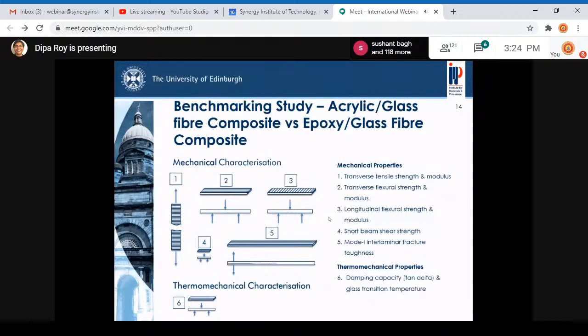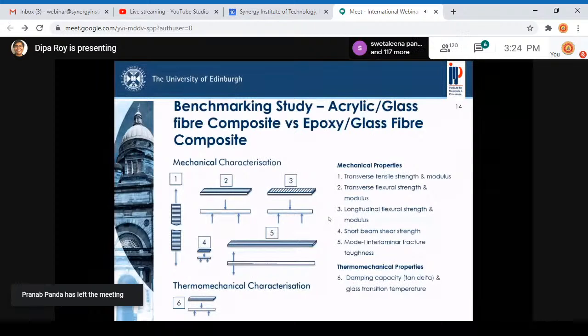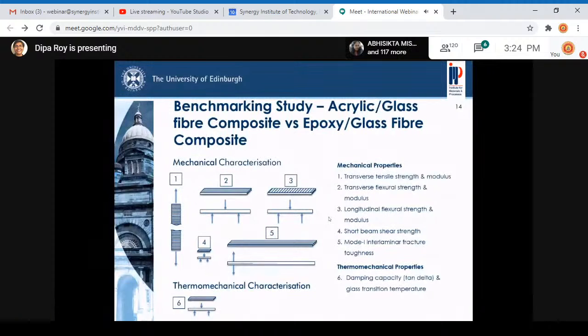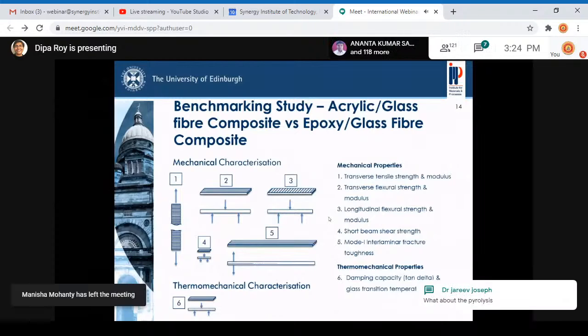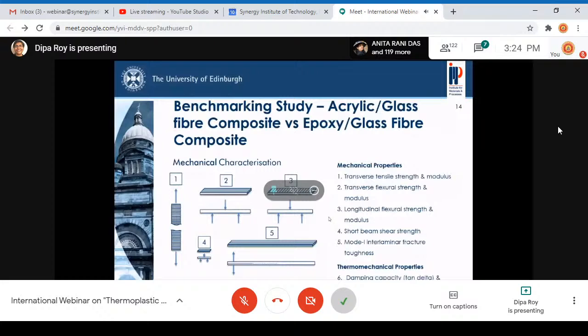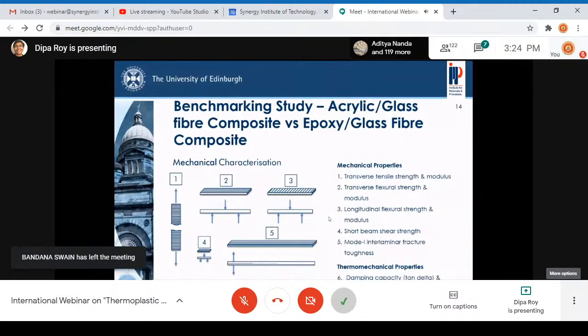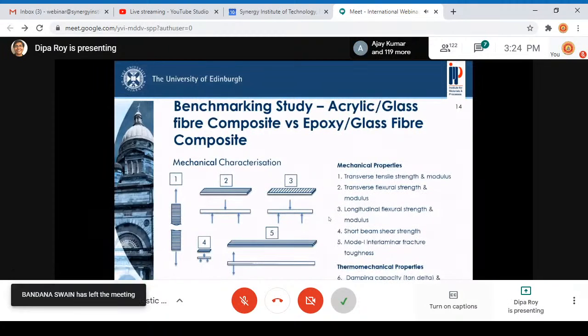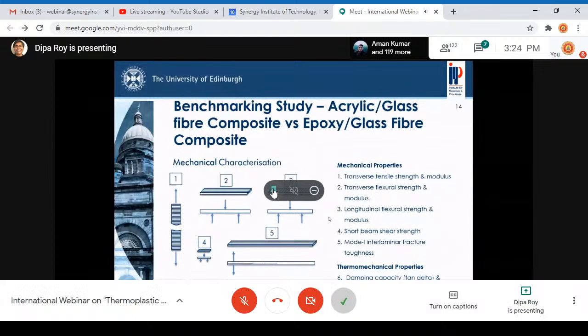So it has those silane coupling agents which have R groups, or organic groups, which are chemically compatible with different matrices. Now, since our acrylic resin is a liquid monomeric resin, it polymerizes in situ during the composite manufacturing. So there is a high opportunity of forming some covalent bonds between the resin and the sizing agent in situ. That's a big advantage of acrylic resin, because we get a chance of forming covalent linkage between the sizing agent and the matrix, which can help in effective stress transfer at the interface.